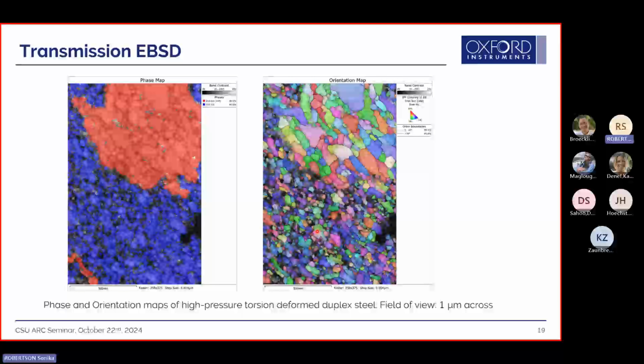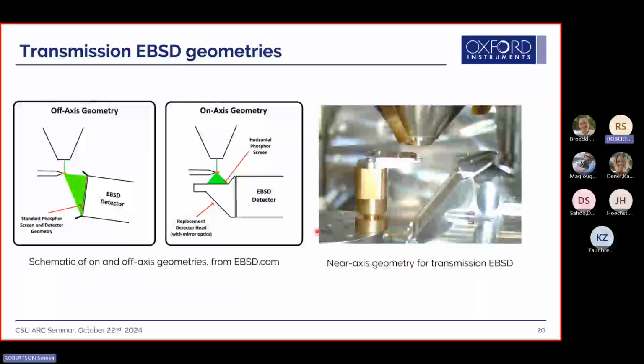You'll just get black everywhere because there aren't enough pixels being picked up in individual grains to give you any useful information. That's why this whole crazy thing about how do we improve the results we can get on the systems. And with transmission EBSD, there are different geometries. So Oxford uses the off-axis geometry.